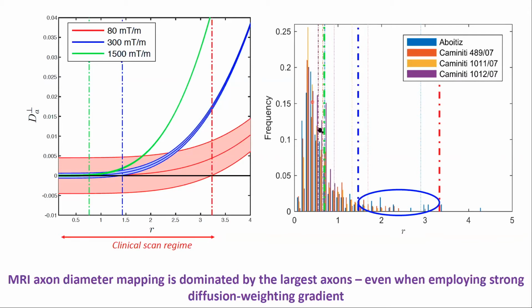If you compare that to the typical distributions that we see from histology, there are barely any axons in that regime. So we're not sensitive to it. If we go to the Human Connectome scanner, the Connectome 3T scanner, then we can see that our resolution limit drops from over 3 to 1.4 micrometers. On the same distribution as this blue line, we start becoming sensitive to this tail. If we can go to preclinical scanners, this limit even decreases, and we can start measuring sub-micrometer. And then we really start becoming highly sensitive to changes here. So even if you go to the strong diffusion-weighted gradients, as for example to the Connectome 3T scanner, MR axon diameter mapping will always be dominated by the largest axons.